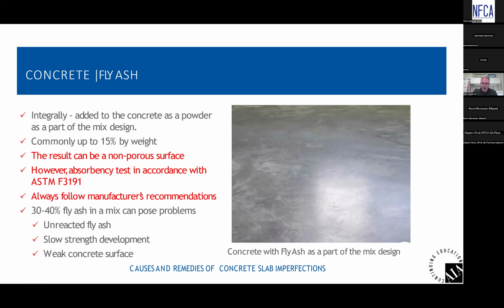It's quite simply dropping water on the surface of materials, letting it sit there for a minute and evaluating the absorbency. Does it soak in and change the color? Or does it just sit there as a puddle? It doesn't change the color. And the point being is adding fly ash to concrete can make the concrete less absorbent.